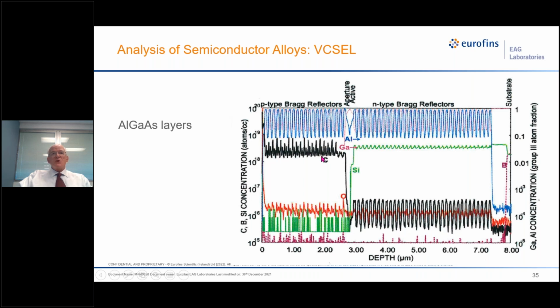But we measure the carbon doping and the silicon doping. And this is the P-type Bragg reflector, and this is the N-type. But we can also measure the carbon impurities that come in with the silicon. And here we have a carbon detection limit in the last gallium arsenide layer, and it's in the mid E15 range. And same with oxygen, it's also in the mid E15 range. But to do this, the machines that do this have vacuums in the mid to low 10 to the minus 11 torr region. So it's a challenge.